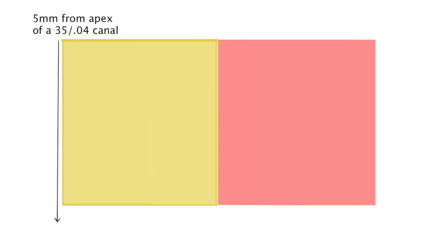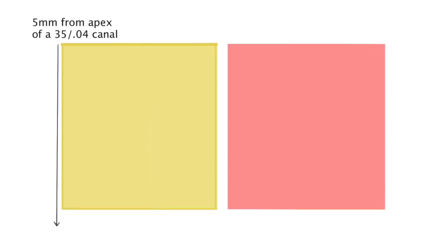So I think if I try to explain my rationale for switching at each instance, it could be helpful in understanding the nature of each cement and the decision making for them. But let's first establish that the sealer's function is to address the shortcoming of gutta percha as a filler. Gutta percha, even when thermoplasticized, has an adaptability problem to the canal, and it shrinks 7% upon cooling. Therefore, we need sealers to fill in these gaps.